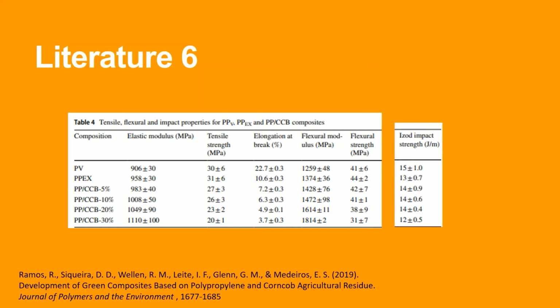The flexural modulus increased significantly from 1,259 megapascal for neat polypropylene to about 1,428 megapascal at polypropylene with 5 weight% corncob content, and continued to increase up to 1,814 megapascal for the composite with 30 weight% filler content. Its flexural strength, on the contrary, decreased as the corncob content increased. The impact strength of the composites is slightly lower than the neat polypropylene, and the significant decrease was observed for corncob content of 30 weight%.